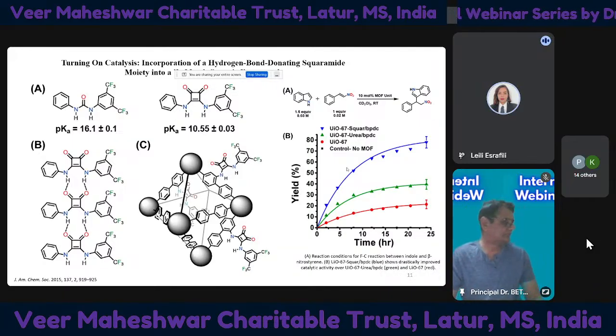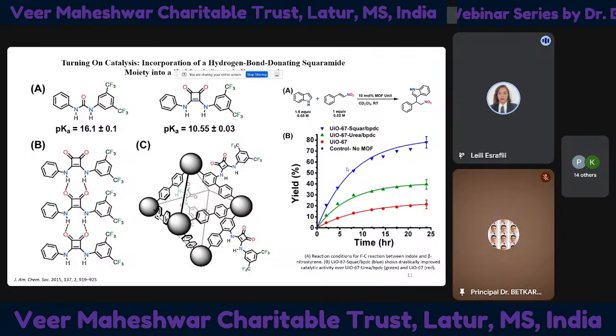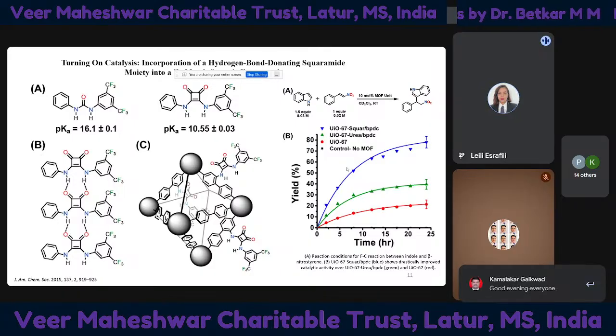I want you to note that with hydrogen bond donors, like when you have urea, thiourea, or squaramide in your linker and you want to synthesize MOF, it is really challenging because these groups tend to form internal interactions during synthesis, and this makes the predictable structure really difficult, and sometimes you end up with a structure you don't want.